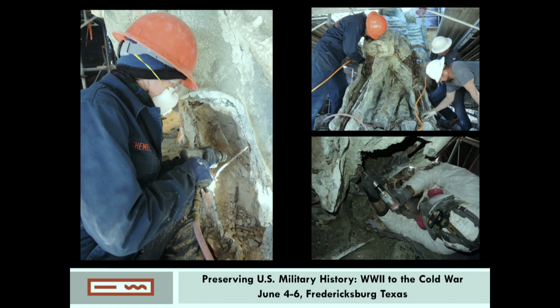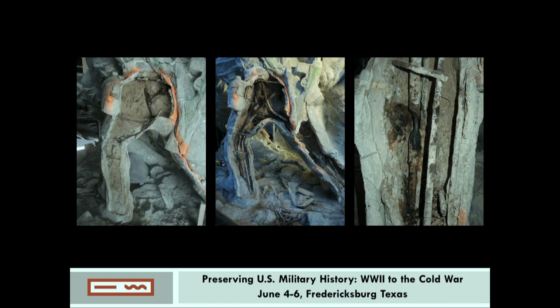Once sections of the shell were removed and the internal clay exposed, these areas were excavated using pneumatic chisels, hand tools, and pressurized water. Corroded sections of steel rebar were then accessible once the clay core was removed and we could really see them. This is the leg of Harold Schultz. Moderate to severe corrosion was visible on the majority of the accessible rebar. In parts of the sculpture that was particularly wet or damp, particularly the feet, because all the moisture was running down to the feet all the time,